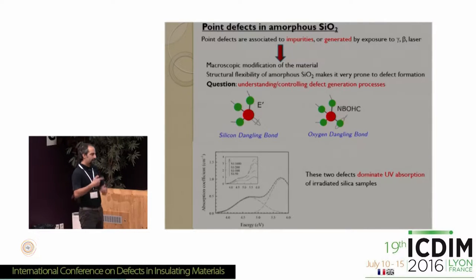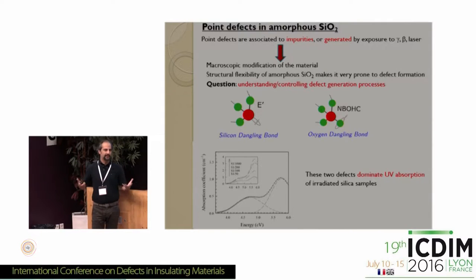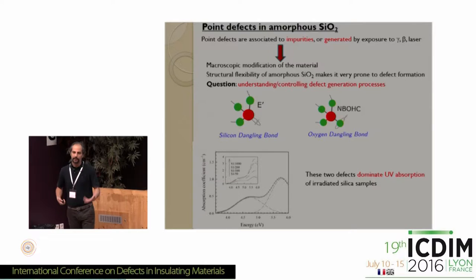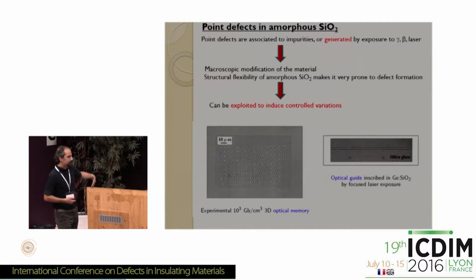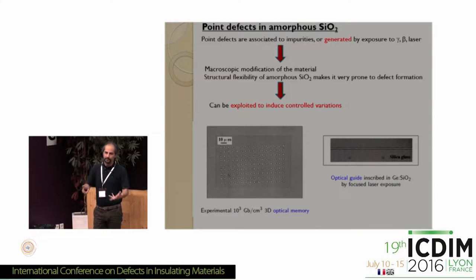Or, by contrast, amorphous SiO2 is endowed with a structural flexibility that makes it particularly prone to defect formation. So these two defects are easier to form in silica than they are in quartz.